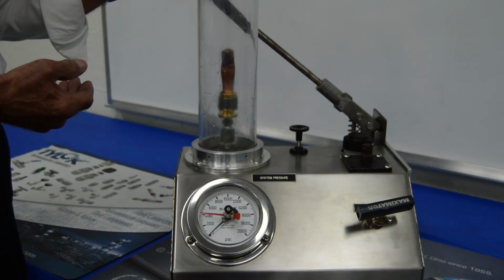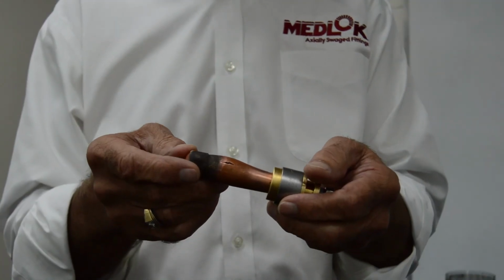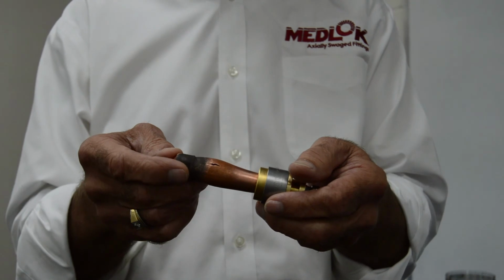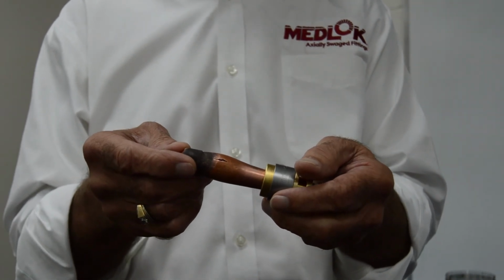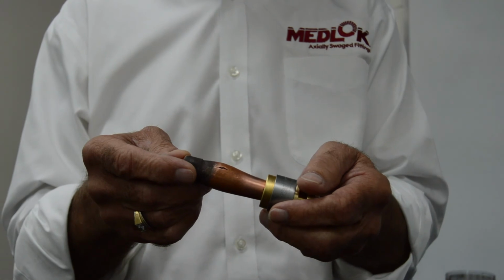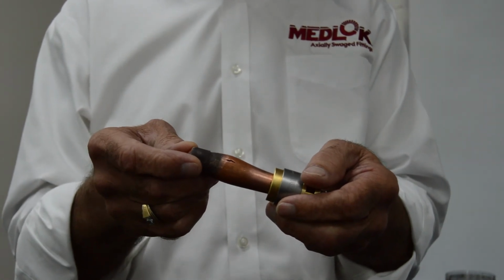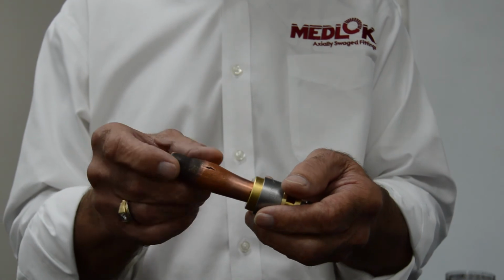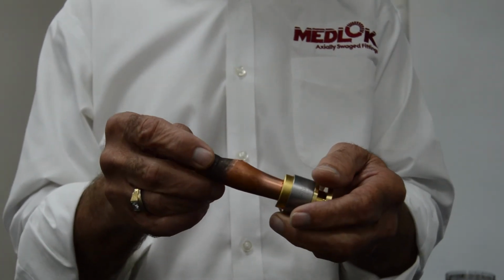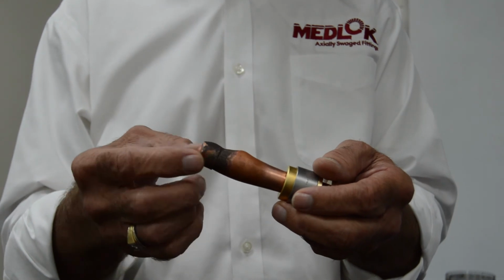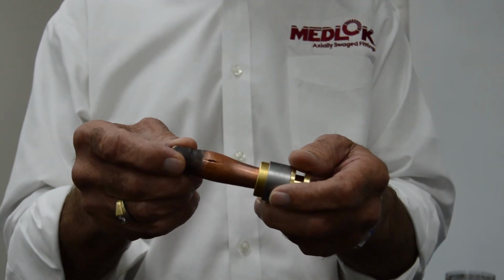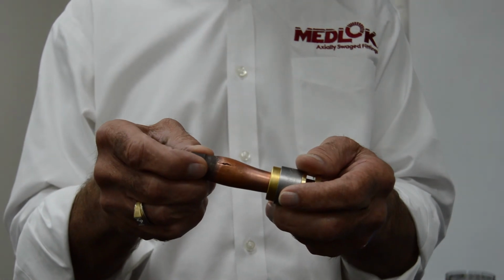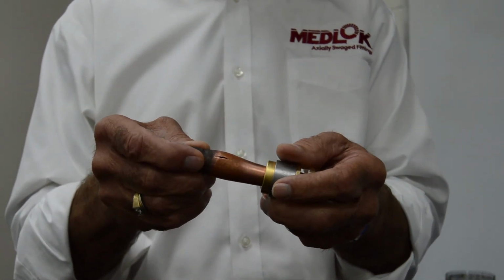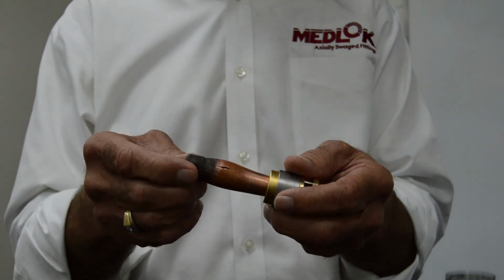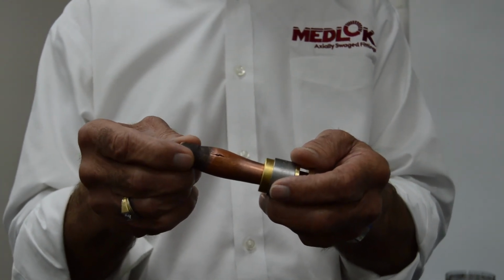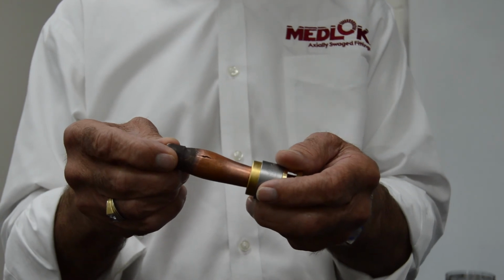In summary, here's a test that we had performed on 1/2" K tubing rated at 1682 in our test chamber that went to 4000 psi before it burst. The tube was fully annealed. As we can see, it expanded during the test, but the Medlok fitting performed flawlessly. As stated in the NFPA 99 requirements, a mechanical fitting should perform with equal performance as the brazed cap, and both of them were able to hold during this pressure test at 4000 psi burst.